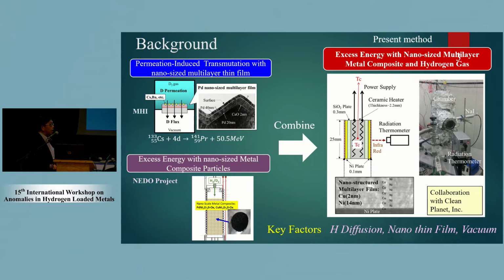After that, I moved to Tohoku University, and I had a chance to participate in the Japanese NEDO project. In the NEDO project, we used nanoparticles, mainly copper, nickel and palladium nanoparticles, and we observed anomalous energy using these particles and hydrogen or deuterium gas. Based on these two research activities, we invented the present method: excess energy with nanosized multilayer metal composite and hydrogen gas.